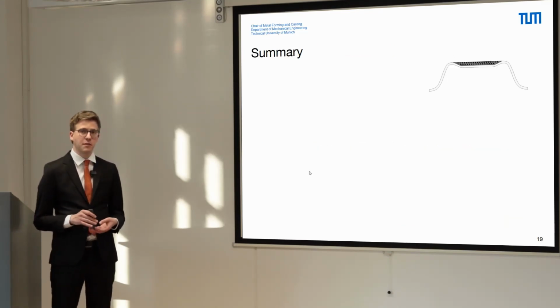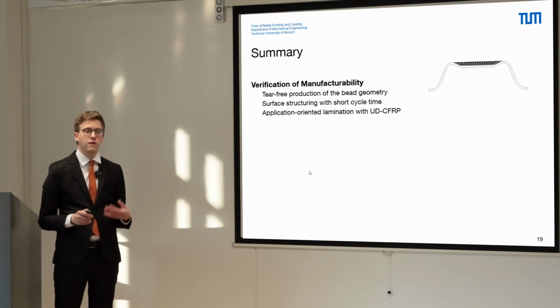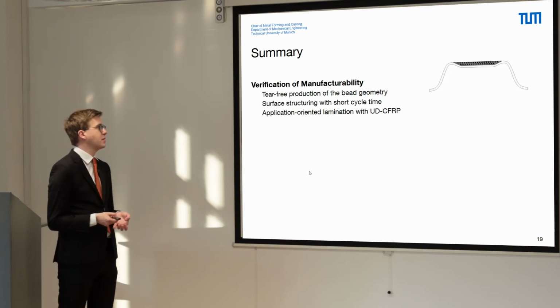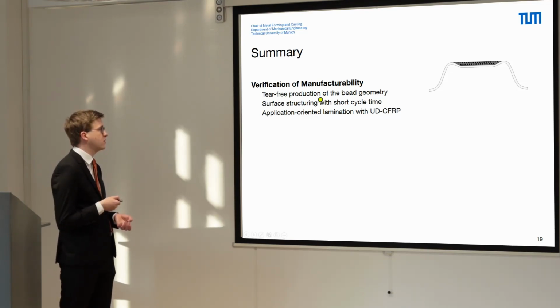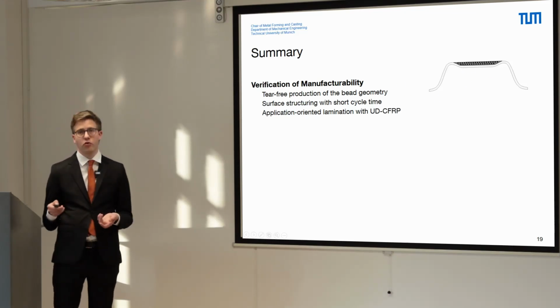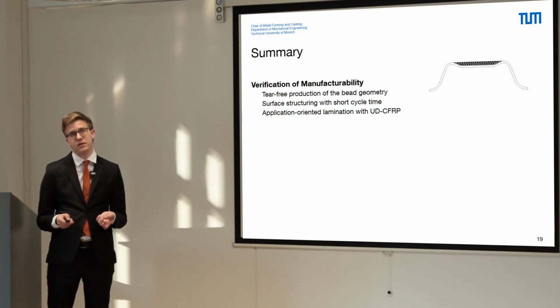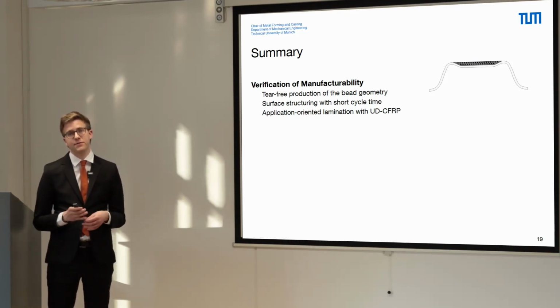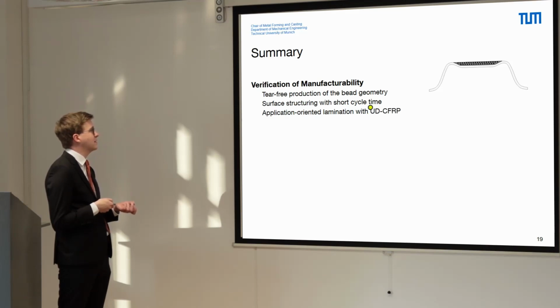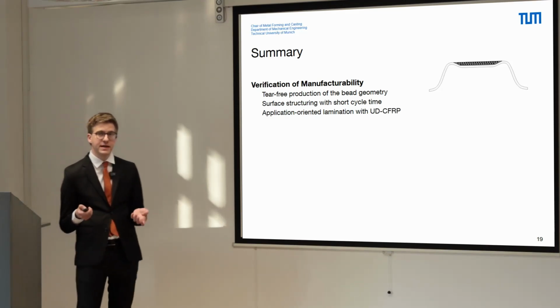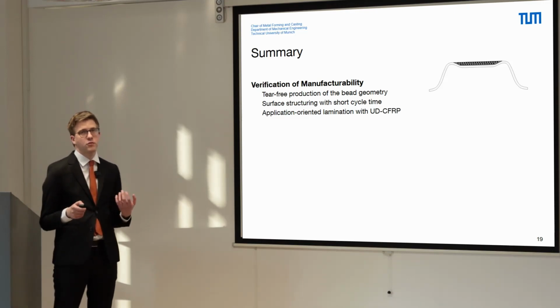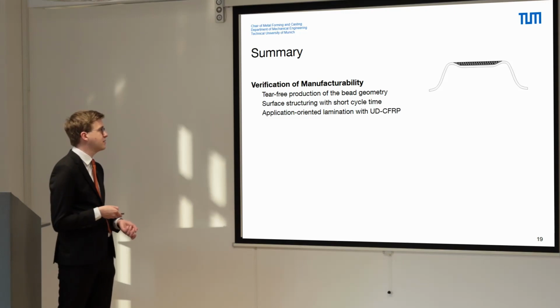To give a short summary of our research work, our main goal was to show the manufacturability of the hybrid bead. First, the tear-free production of the adapted bead geometry. Second, the surface structuring, which both show a short cycle time of less than 30 seconds for both the laser mechanism as well as the sandblasting mechanism. And third, an application-oriented lamination process with the AFP-based strategy which we used. So we would advise using this lamination method for further implementations of the hybrid beads in industrial applications.